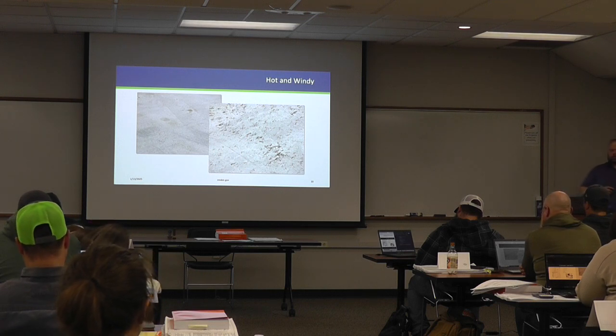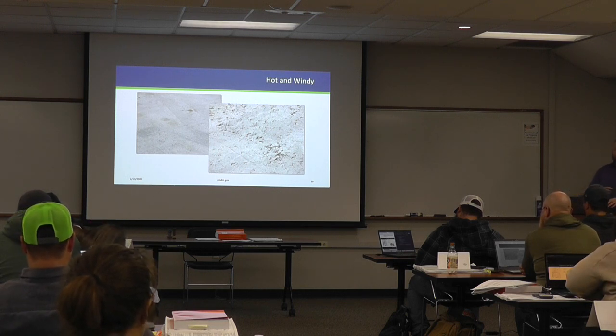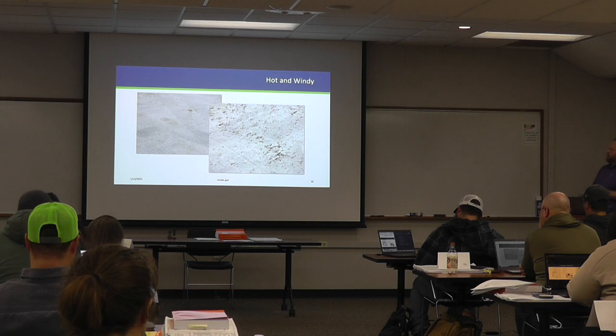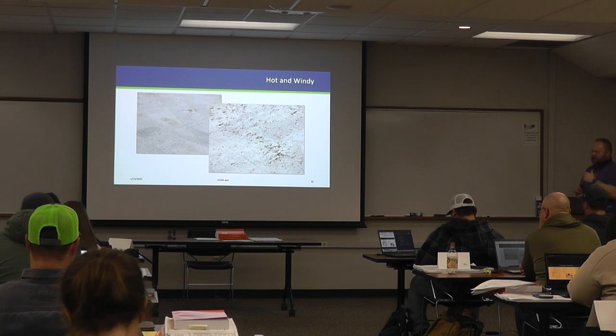But these are things that can happen if we're not aware of our evaporation rate, where that surface might start drying up and we can't finish it, we can't close it up. We might start getting plastic shrinkage cracking or crazing or dust and things like that. That's why we want to be aware of conditions when we place the concrete.